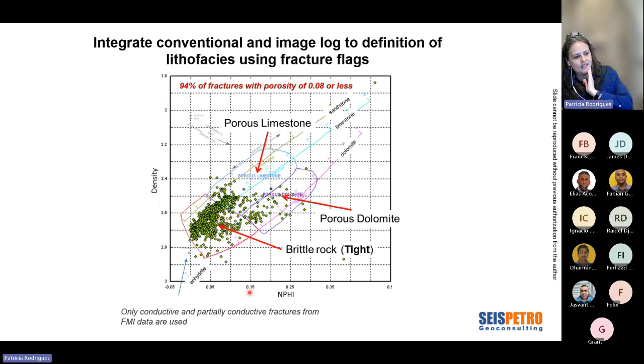So what we did here was a neutron-density cross plot. We have your sandstone, limestone, and dolomite lines. The points shown here are only the conductive or partially conductive fractures that we saw in the FMI. Based on this, we selected 8% as a cutoff because 8% had 94% of the fractures. So 94% of the fractures that we saw in the FMI were found when the rock was tight, and tight here was defined as less than 8% porosity.